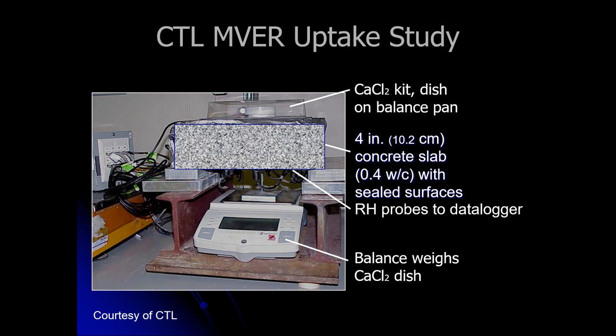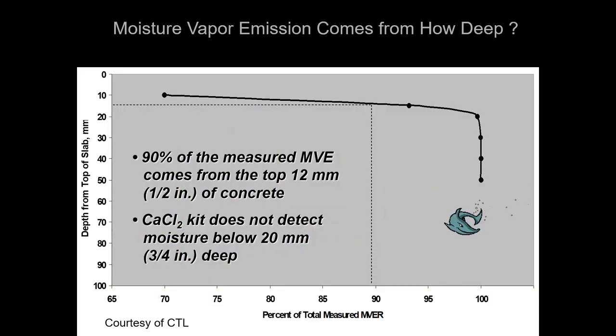But when they were there together, they set up a test where they took a 4-inch concrete slab that had relative humidity sensors embedded into the concrete. So they could determine where the moisture that the calcium chloride pearls were absorbing was coming from in the composite depth of that slab. And what they found was that the only moisture being absorbed into the calcium chloride pearls during the time period was coming from the top half to 3/4 of an inch, which meant that there was still a significant reservoir of unmeasured moisture deeper in the concrete that this test just told us absolutely nothing about.